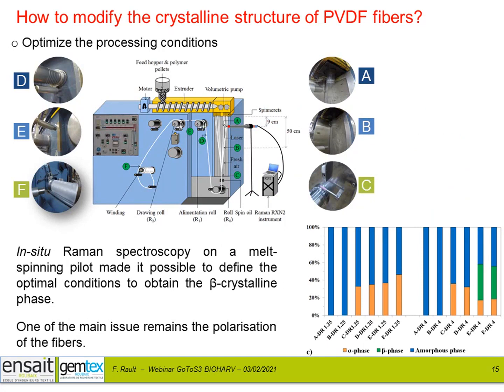In the Autonotex project, we again studied the optimization of the beta phase content of our filaments by adjusting the conditions of the melt spinning process. To achieve this, we carried out online monitoring of the crystal structure using Raman spectroscopy. This allowed us to select the process parameters more precisely. Nevertheless, one of the main issues remains. I mean the poling of the filaments.